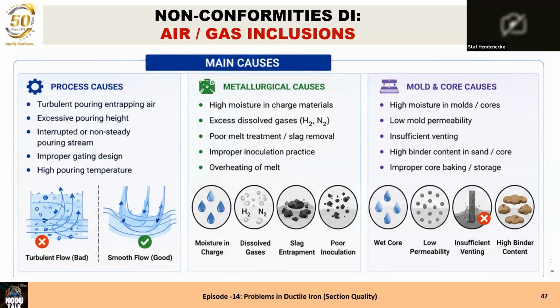Metallurgical causes, of course, high moisture. I don't have to tell you guys in India that during the monsoon season, it's a very frequent defect that every one of you has seen. Excess of dissolved gases, H2 and N2. The H2 is caused from the humidity. And the next one is a poor melt treatment, but the poor melt treatment is mainly the slag removal.